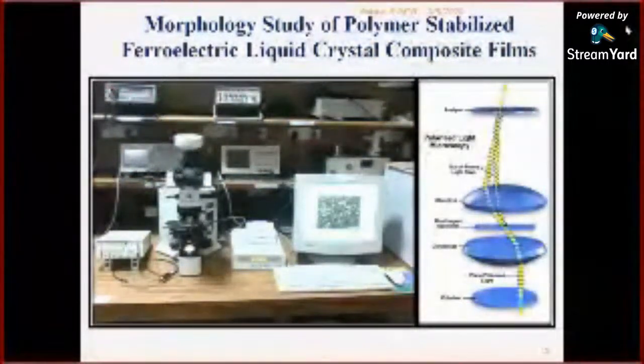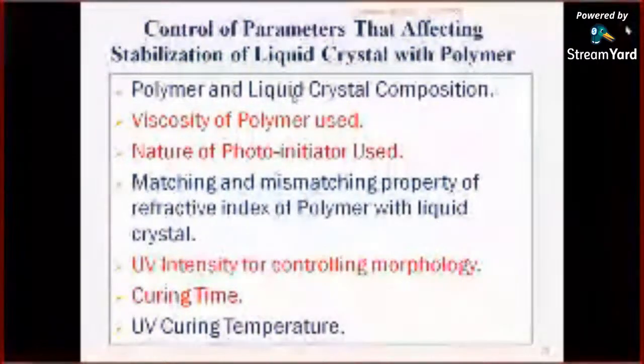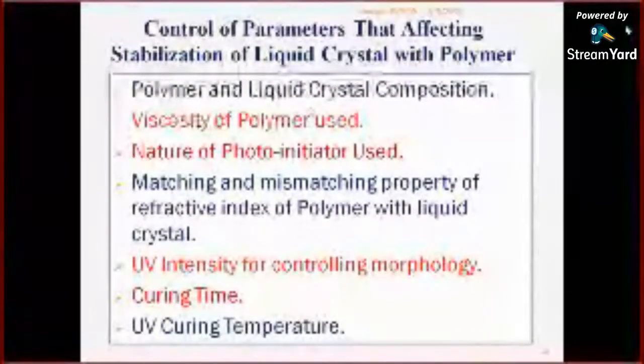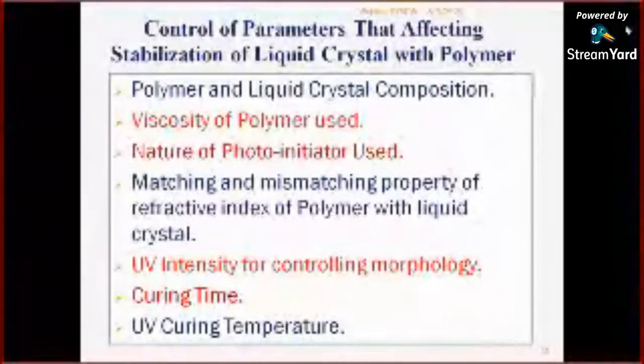So next, how the control of parameters affects the liquid crystals with polymers. The polymer and liquid crystal composition is the major parameter. We can change the polymer and liquid crystal composite, and then we can form different types of liquid crystal composite materials, and study different types of electro-optic as well as dielectric properties. So all these parameters, viscosity, photoinitiator, matching and mismatching of polymer and liquid crystal, curing time, UV curing temperature, are used to study the liquid crystal composite material.